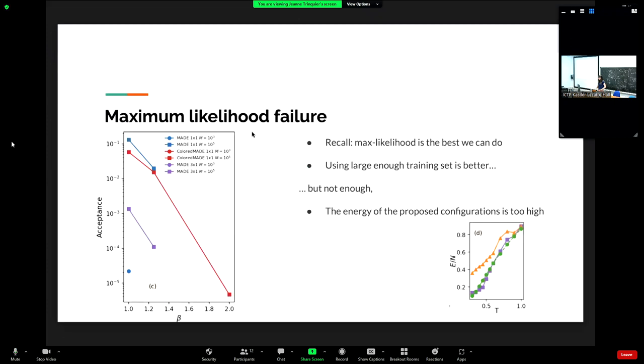So the maximum likelihood fails. It is a good model, with an acceptable acceptance rate at high temperature, but as soon as you try to decrease the temperature, the acceptance rate goes to zero, basically, for all kinds of models. We tried to use larger training sets and more expressive models, but everything fails. And in all cases, the energy of the proposed configurations is too high in comparison with the energy of the equilibrium model.